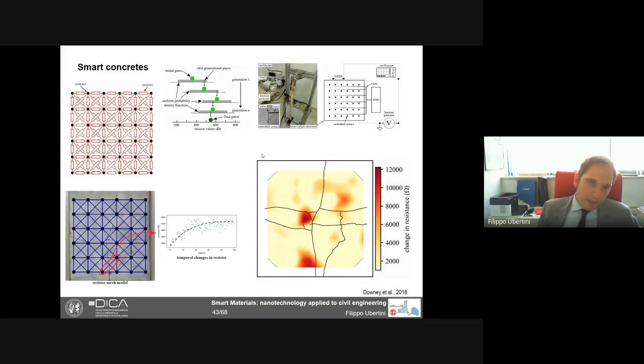And by the way, if you look at the temporal changes in one single resistor, see the left-hand side of the slide, then you see that the resistance actually increases with time, which means with the number of impacts. So somehow we are not only able to detect where the damage is located, but also to quantify its severity.